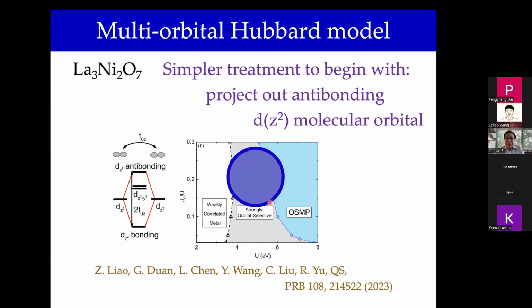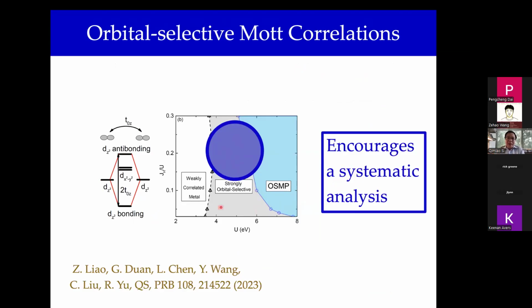It is believed that the realistic interactions for the nickelates are somewhere in this blob, and you can see that this blob corresponds to the regime where there's a strong orbital selectivity in the correlation effects, meaning that the quasi-particle renormalization factors between the different orbitals are substantially different. And so this gives the encouragement to proceed and do more systematic studies of the correlation effect. Again, it's early going, so we want to orient ourselves, and the way we orient ourselves is to carry through these orbital-selective correlation calculations and see how they compare with spectroscopy results.